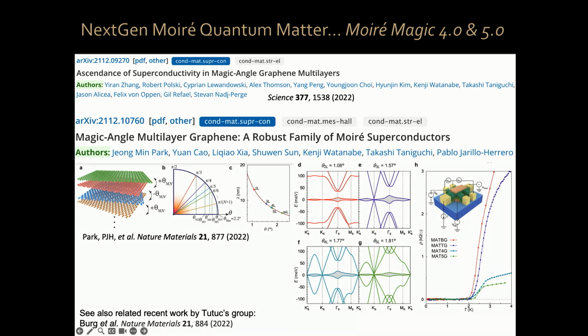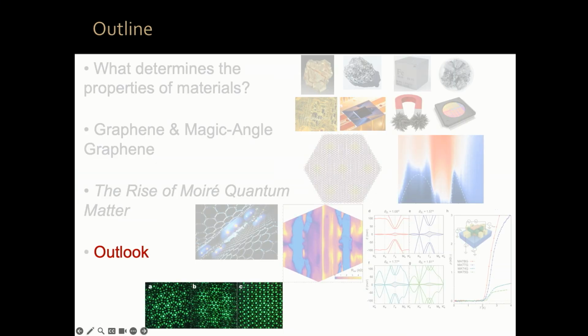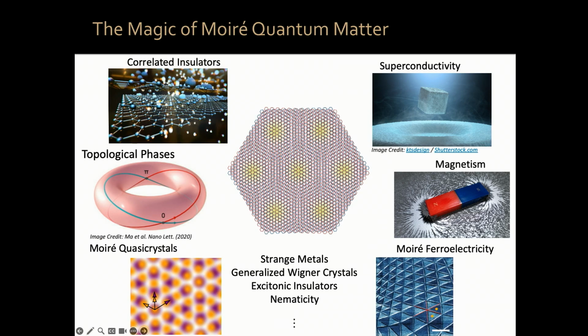Now, in the last couple of minutes I've been talking mostly about electronics so far, but it turns out all of these concepts extend beyond electronics, and also beyond graphene and transition metal chalcogenides. We've been realizing all of these phases of matter with pretty much just carbon. In some cases, also with hBN or with the transition metal chalcogenides. You can realize most of them with pure carbon, because you can play with the angle and the density of electrons. Playing with the density of electrons in these superatoms, this Moiré structure, is the equivalent of going through the periodic table, and that's where part of the physics comes from.